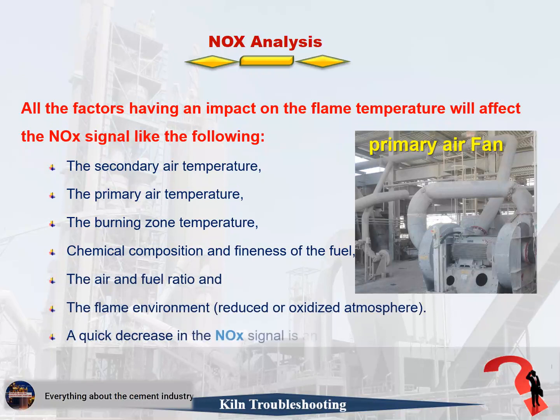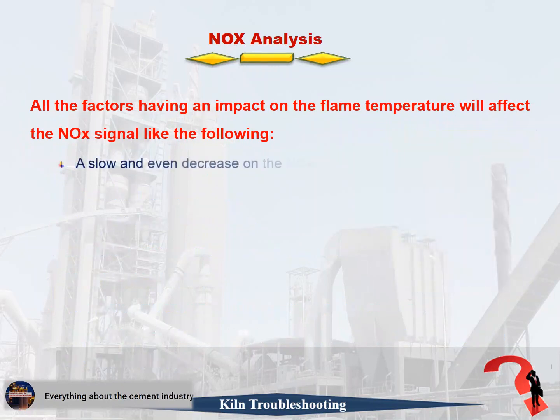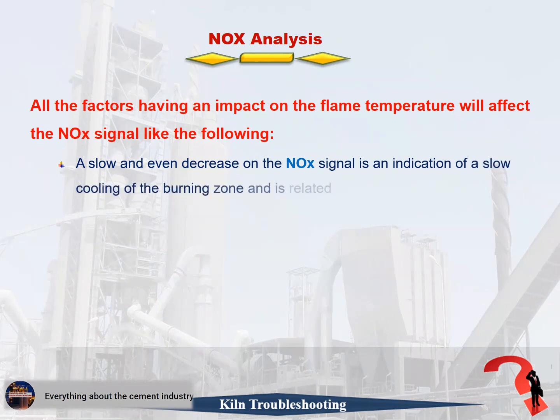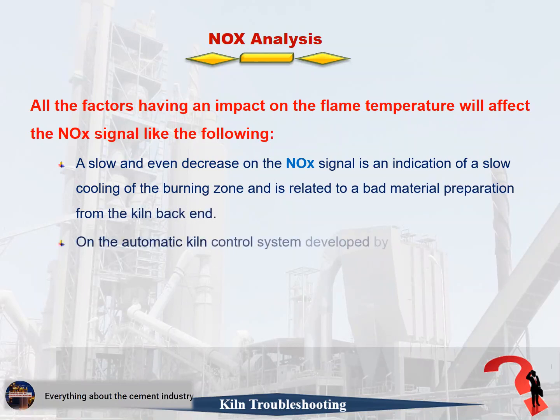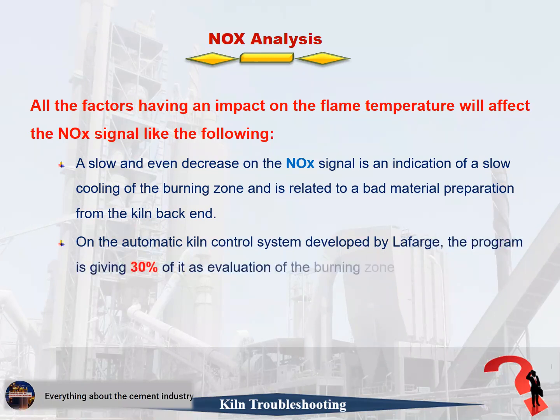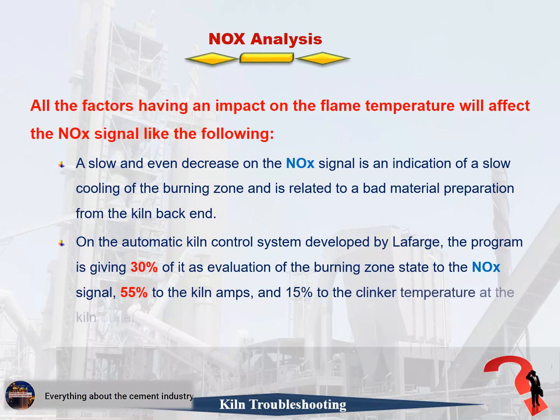A quick decrease in the NOx signal is an indication of the burning zone temperature dropping. A slow and even decrease in the NOx signal is an indication of a slow cooling of the burning zone and is related to bad material preparation from the kiln back end. In the automatic kiln control system developed by Lafarge, the program gives 30% of the evaluation of the burning zone state to the NOx signal, 55% to the kiln amps, and 15% to the clinker temperature at the kiln outlet.